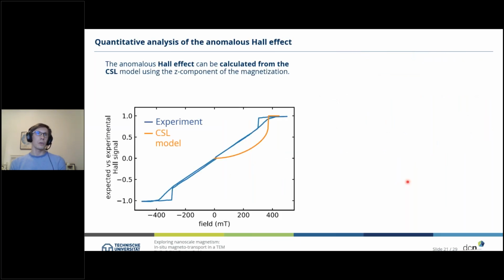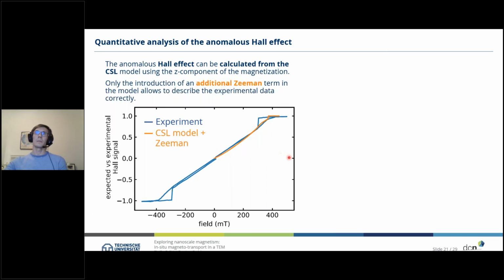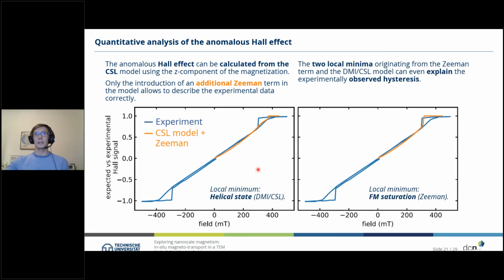But we also measure, of course, the Hall voltage. Now we're using that model where we know the magnetic configuration as a function of field. By just plotting the Z component, we see that this does not fit the Hall voltage which we measure. So there seems to be something missing. Only if we add an additional Zeeman component to our model, we can nicely reproduce the experimentally observed Hall signature and also find local minima which describe the hysteresis in our sample.